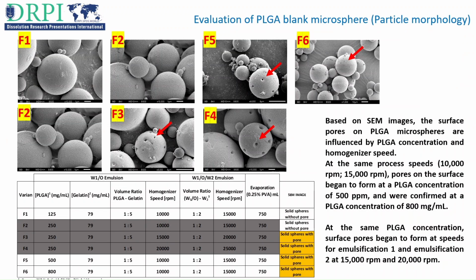Morphological evaluation of blank microspheres showed that at the same emulsification speed, porosity was first observed at a PLGA concentration of 500 mg per milliliter. At the same PLGA concentration, porosity began to form at emulsification speeds of 15,000 and 20,000 rpm respectively.